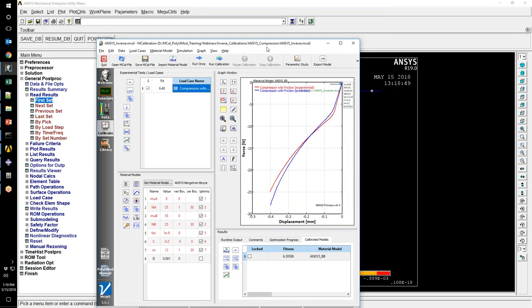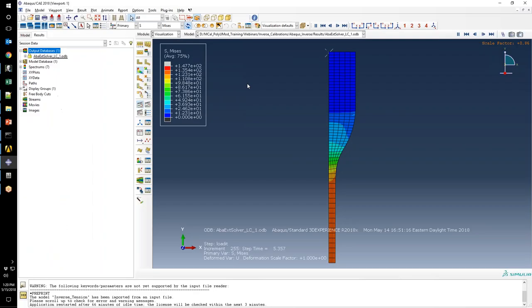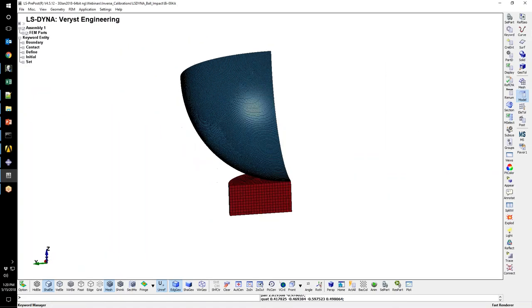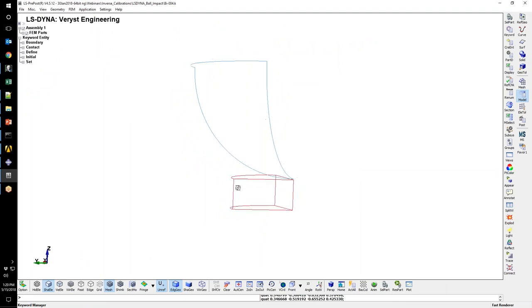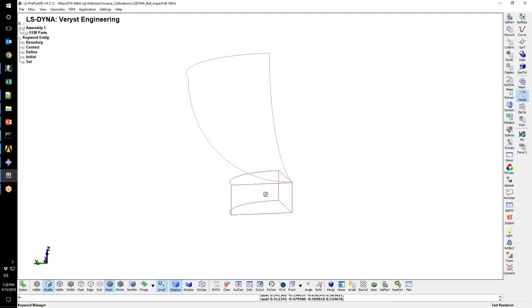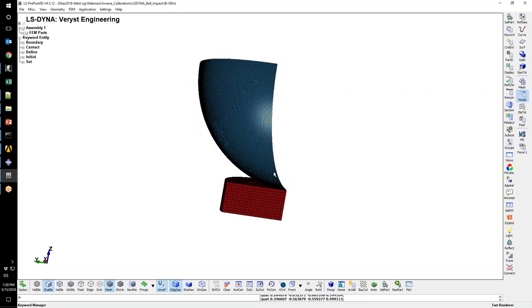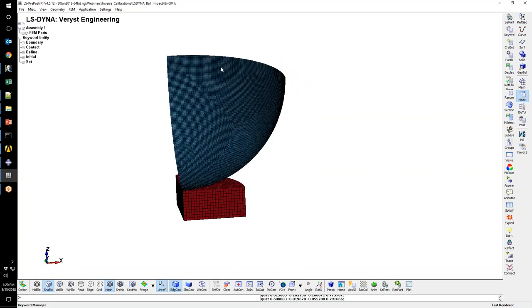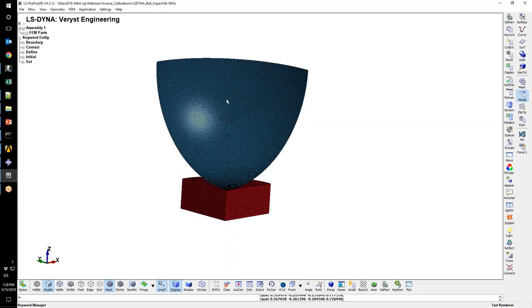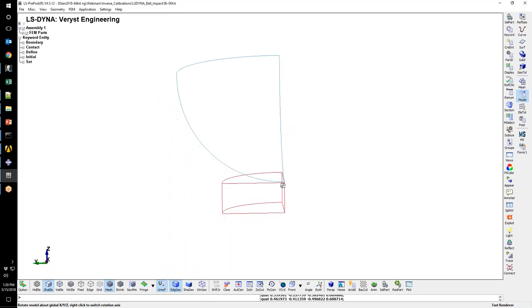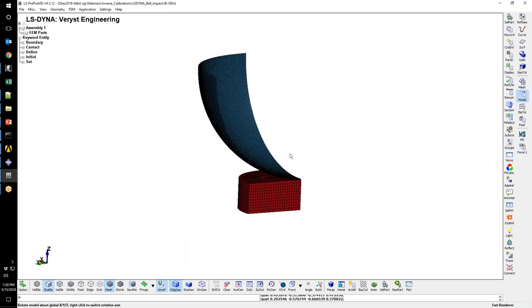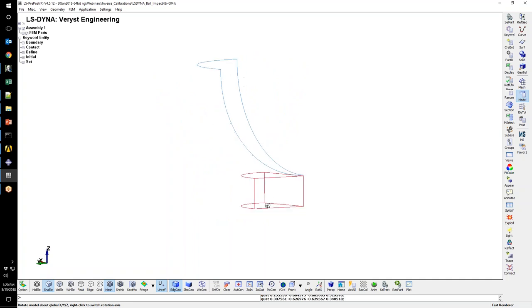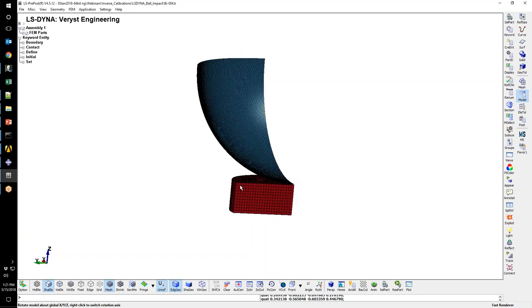I have one last example that I'm going to show you, an LS-Dyna ball impact experiment. The easiest way to show you is with the model itself. The model here - the red is the sample. I'm using quarter symmetry, so this is just a small thin cylinder. This blue, these are shell elements, rigid elements that model a steel ball. In this experiment we take the ball, we drop it from a known height, in this case about 25 inches. The ball comes down, hits the sample here, and rebounds up. We measure the force from this and calculate the displacement based on the problem. I've set this up with shell elements, I've added extra mass to all these elements so that we have the true mass of the ball. I've given the ball an initial velocity and I have gravity acting on it in the downward direction.